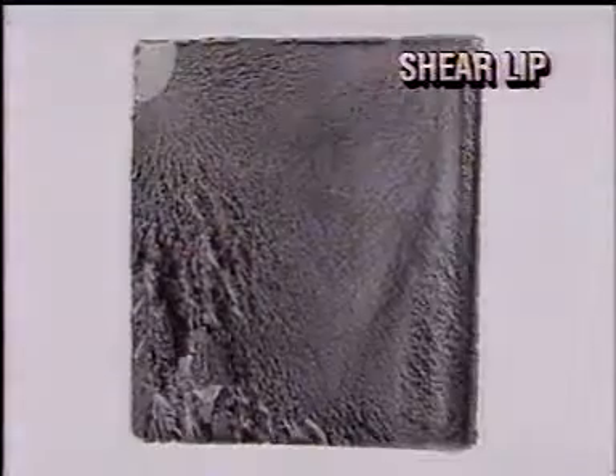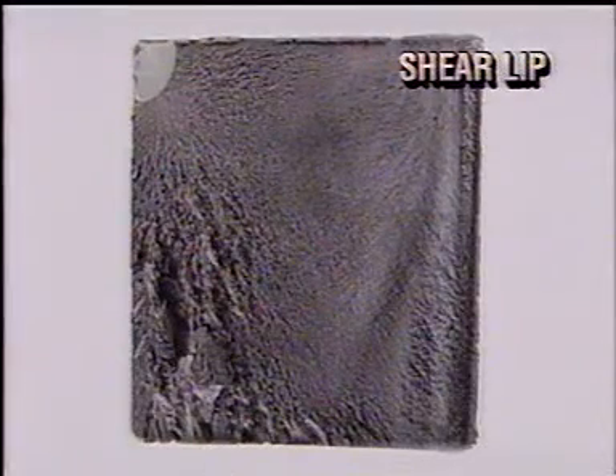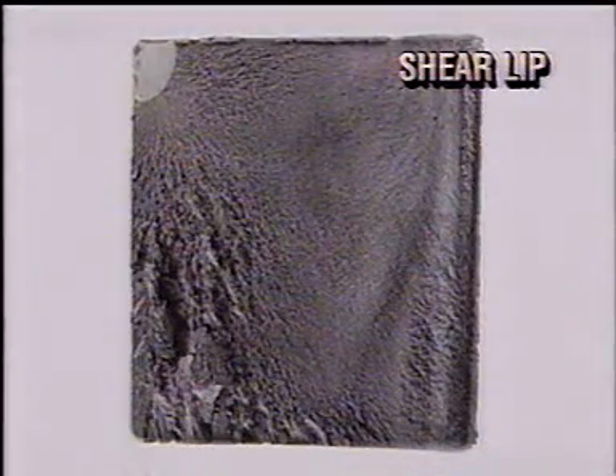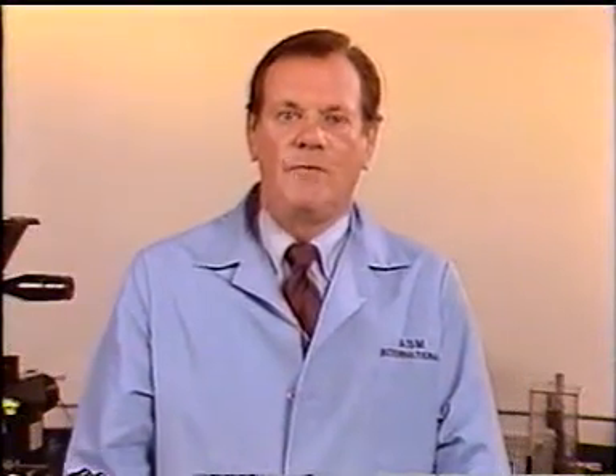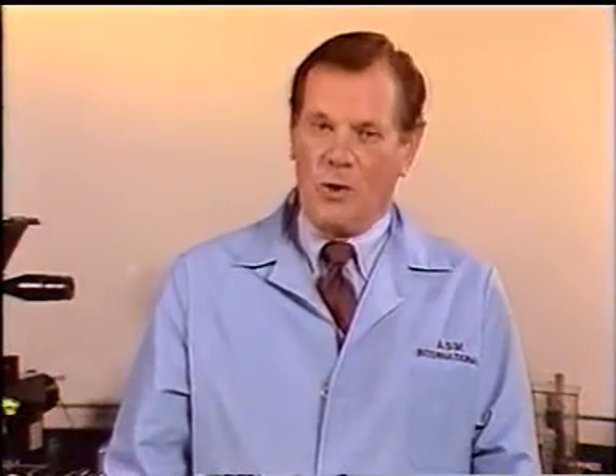Sometimes the slant fracture or shear lip of the ductile fracture resembles a picture frame on a relatively thick rectangular section. The shear lip shows that the fracture emerged from the interior of the metal at that location. Service failures caused solely by ductile fracture are relatively infrequent. When they do occur, the structure or machine component is often stated to have failed as the result of a single overload, as from an accident.